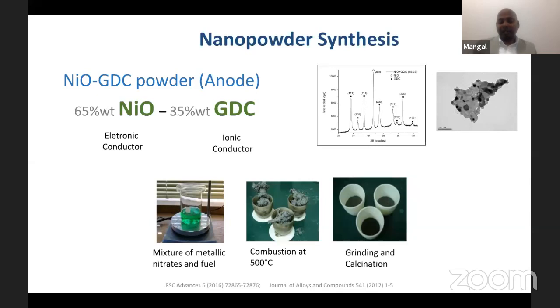particles. So it is not a big task nowadays. But still we have focused on rapid synthesis of making fine particles through combustion methods. In this way, we adopted this combustion method for synthesizing three materials: anode, electrolyte, and cathode. For the anode, what kind of materials did we choose? Nickel oxide and gadolinium doped ceria composite, in the ratio of 65% nickel oxide and 35% gadolinium doped ceria. As I mentioned earlier, it has to be an electronic and ionic mixed conductor. Also it should be porous. So I will tell you how it was fabricated.